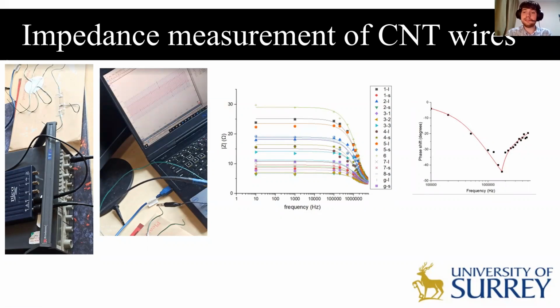I've also found the phase shift with an increase of frequency, which gave me an interesting result. The dip occurred at a different frequency than the dip observed with the magnitude. This is very interesting, as I would be expecting the dip to occur at a resonance frequency. This would imply that the CNT samples had either multiple resonant frequencies or there were some other factors at play which affected it.